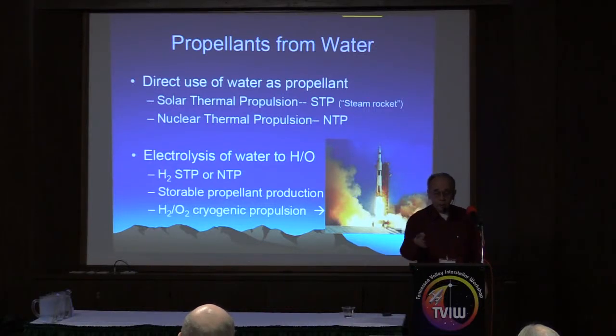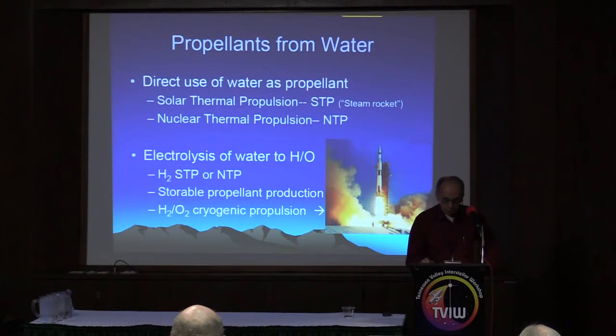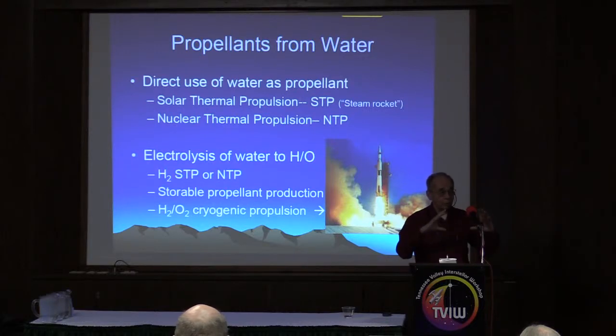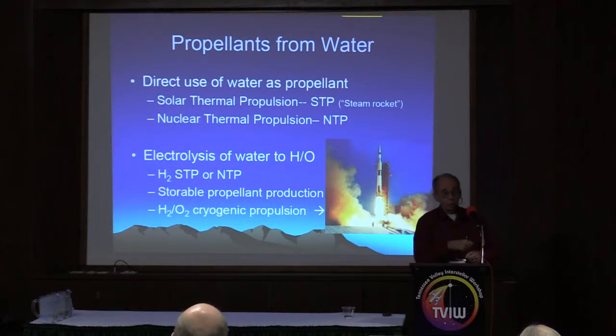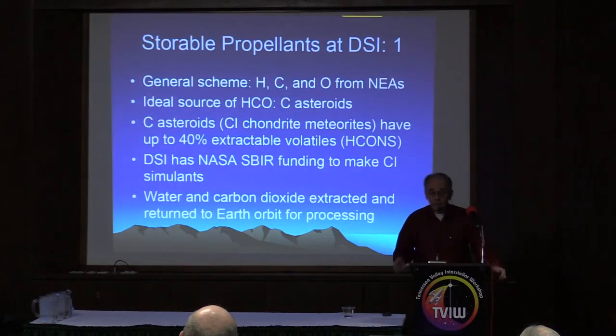Electrolyze the water to hydrogen and oxygen. You can use the hydrogen for solar thermal propulsion with extremely high specific impulse. You use a refractory material such as rhenium or thorium oxide to manufacture a thrust chamber. You use a solar collector to focus sunlight onto the thrust chamber, and you trickle water or hydrogen into that chamber, and it comes roaring out at up to 3,000 Kelvin. Tremendous performance. Or you can do cryogens, right?